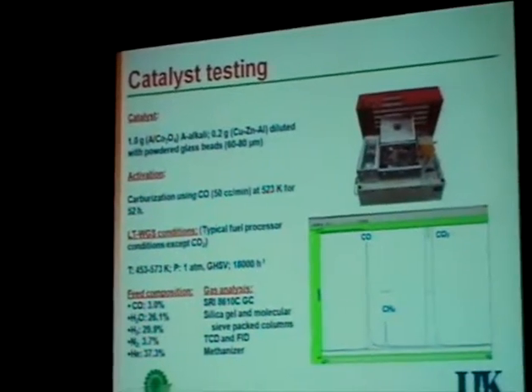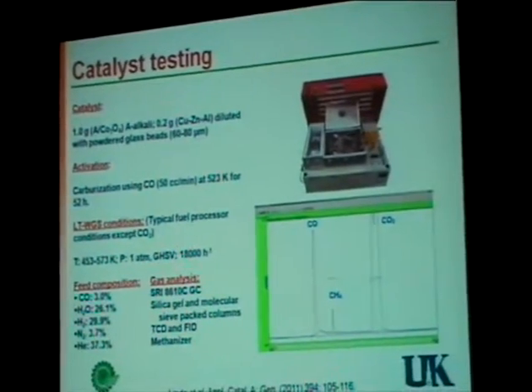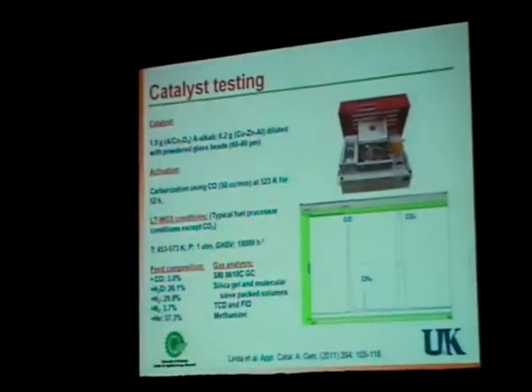We varied the temperature from 453 to 573 K, that is 300 degrees Celsius. And the components being analyzed, CO and CH4 and CO2, using the SRI GC. It contains both silica gel and molecular sieve columns. The detectors are TCD and FID. And in order to boost the CO2 detection, we have that mechanism to boost the detection of CO2.